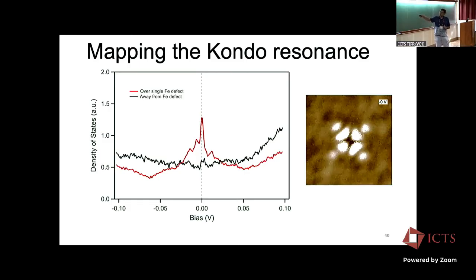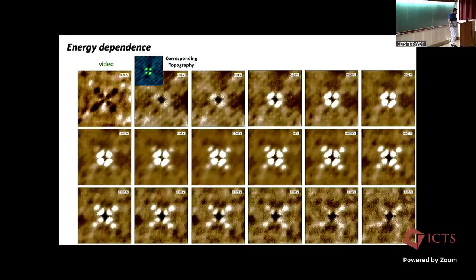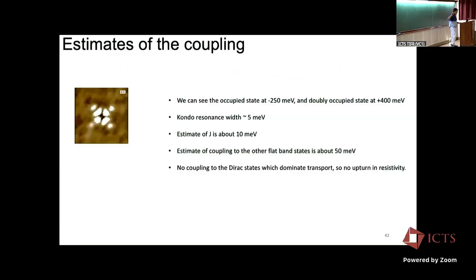Not only this, we can actually image both the singly occupied and the doubly occupied states. If you go below the Fermi level, you can image the singly occupied state. If you go above the Fermi level, sorry, I'm jumping a little bit. Okay. We can image both the singly occupied and doubly occupied state. They live below the Fermi level, above the Fermi level. We know the Kondo resonance width. We can estimate the J in the Kondo from this. And we can estimate the coupling to the other flat band states by sticking it into the formula.